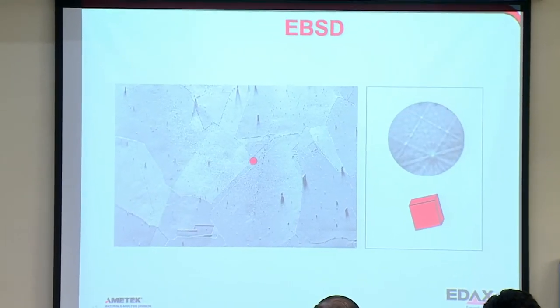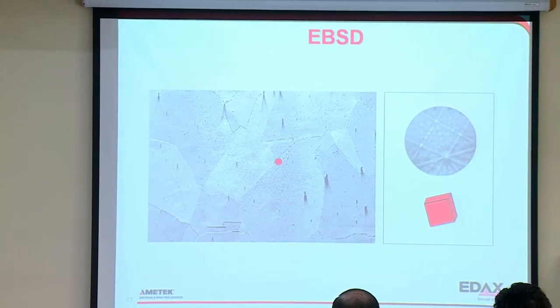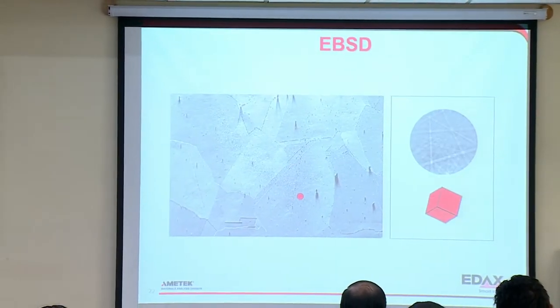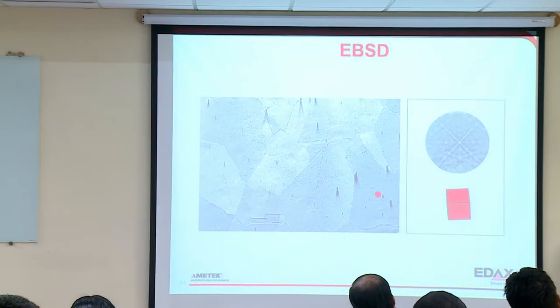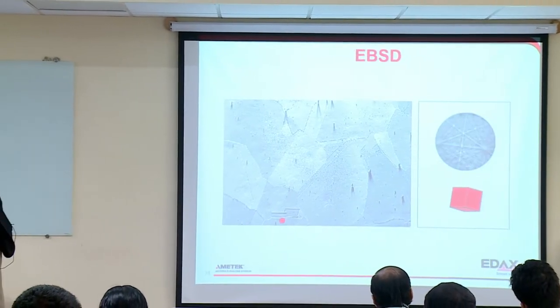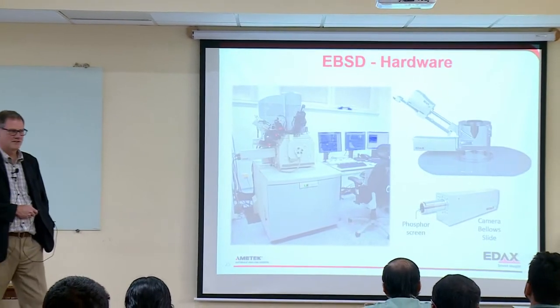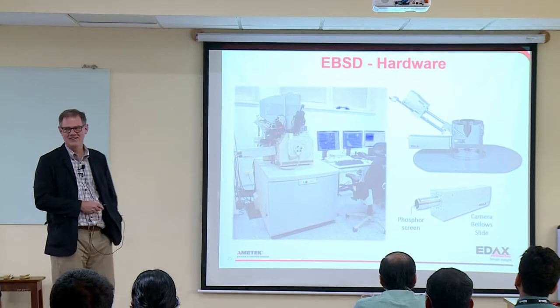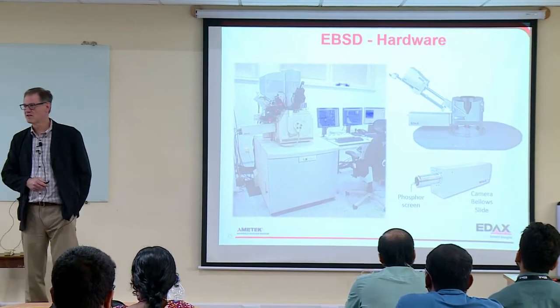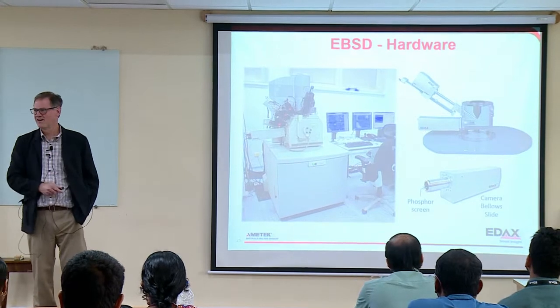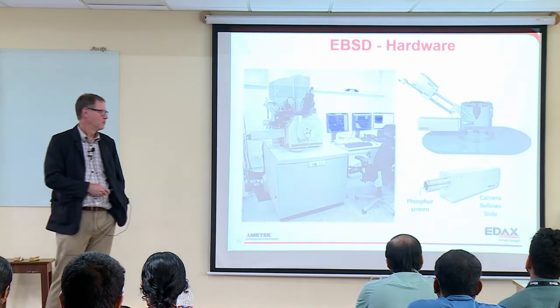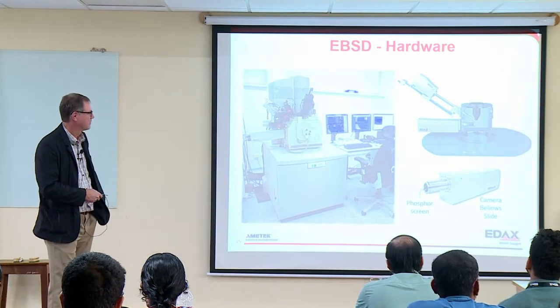If I move the beam, I get a different pattern because it's a different orientation. And I can just move the beam around the sample and you get nice patterns. And you hope you get nice patterns. Some samples are a little tougher, and some of you have probably experienced that sometimes all you see is gray and no bands at all. But we'll come back to why that can be.